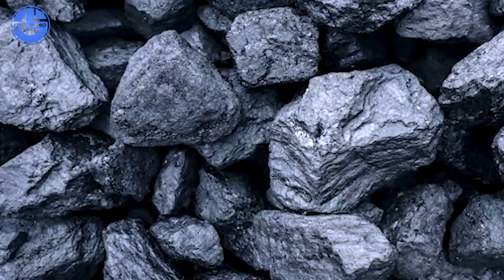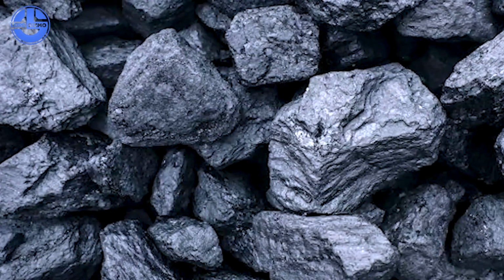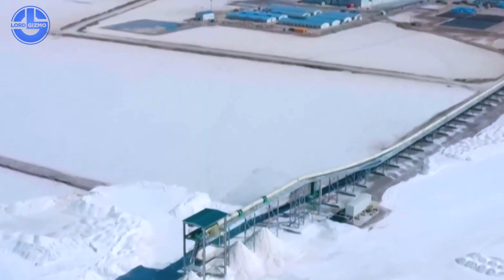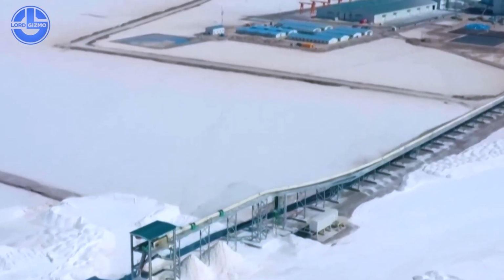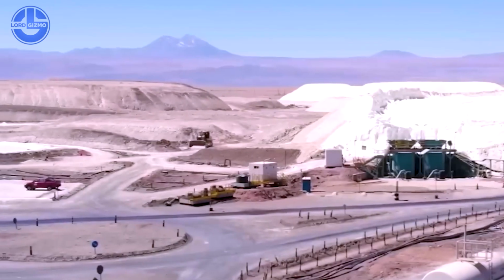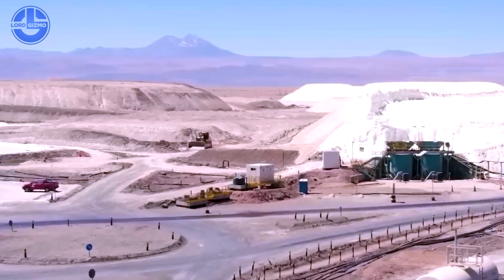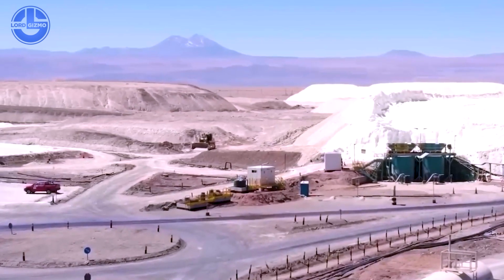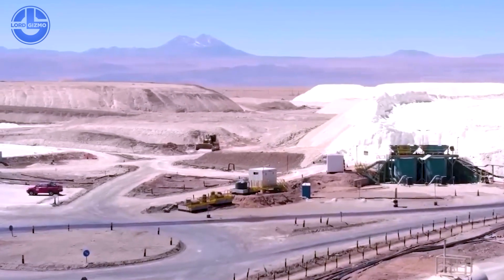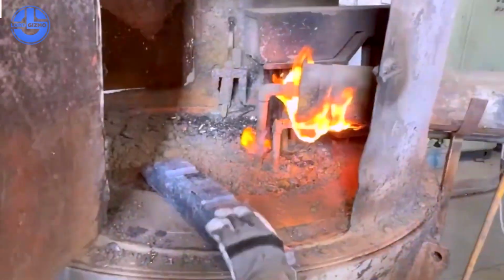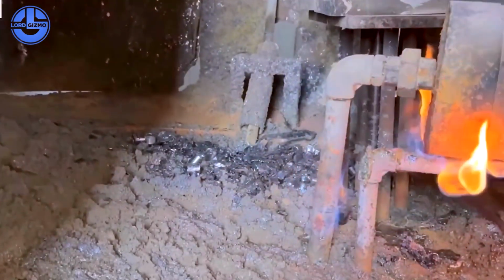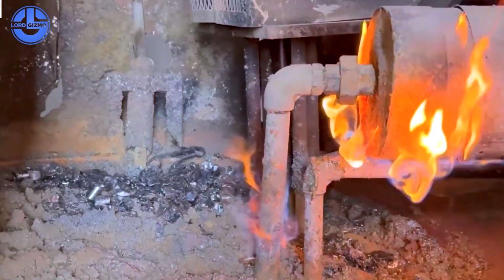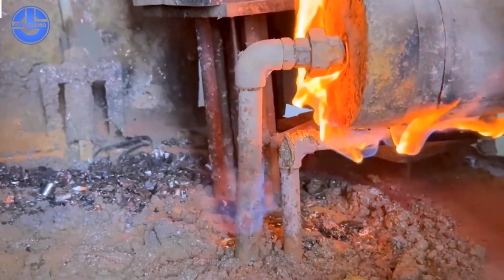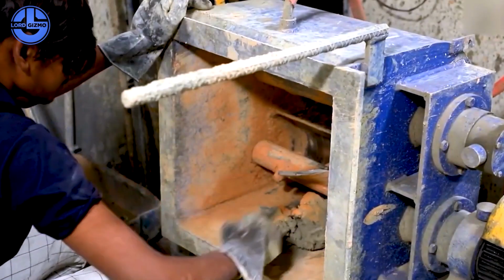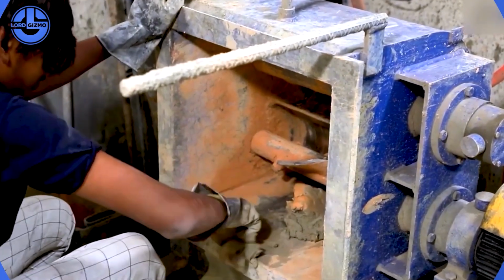The graphite story is equally remarkable. While natural graphite exists worldwide, nearly all the processing happens in China because they mastered the art of transforming raw graphite into battery-grade material decades ago. This processing involves heating graphite to temperatures exceeding 2,800 degrees Celsius, hotter than volcanic lava, to achieve the perfect crystalline structure needed for lithium storage.